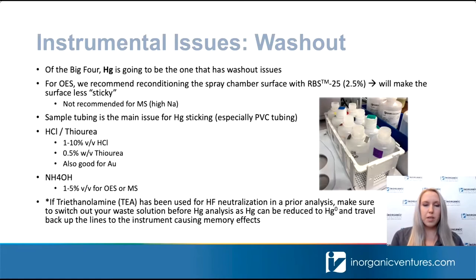Another thing we've learned from experience is if you do have TEA or triethanolamine in your wash solution, make sure that you're switching that out before conducting your mercury analysis. A lot of times we recommend adding TEA to solutions with HF if you don't have an HF resistant system, because the TEA will neutralize the HF and prevent any issues with HF in your glass components.